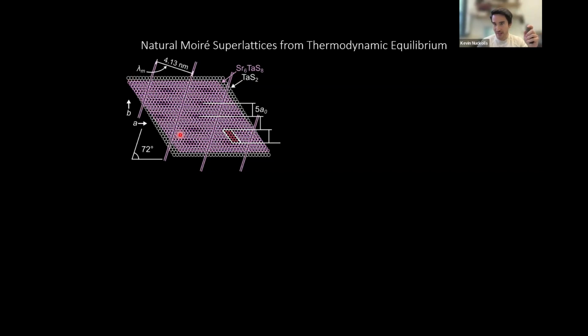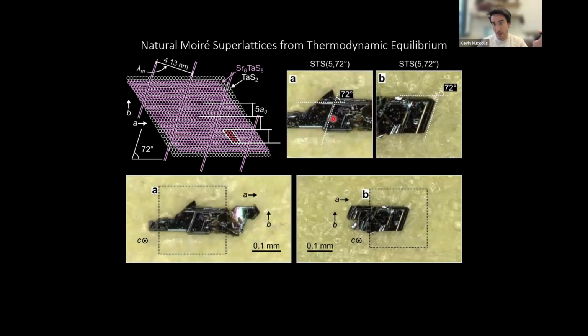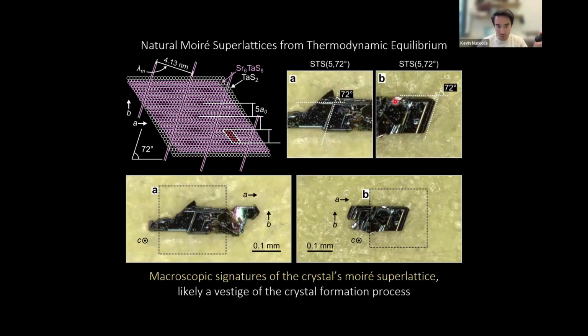But really perplexingly, if you look at these crystals under an optical microscope, you can actually find obvious crystal step facets and even macroscopic crystal facets that all align to the 72-degree angle. So this is really beautiful. This is a macroscopic signature of the crystal's Moiré superlattice in optical microscopy, likely a vestige of the crystal formation process.